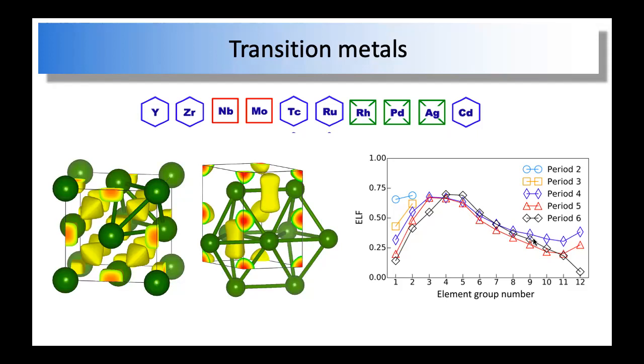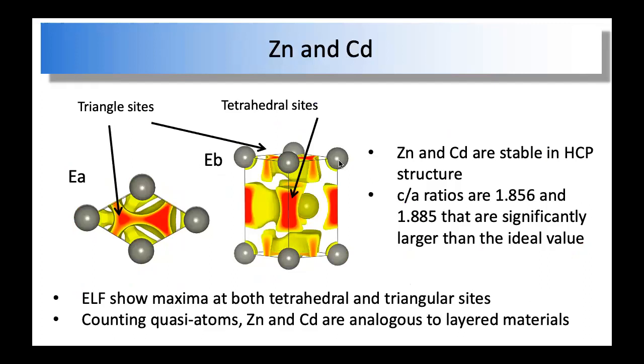So eventually, the localization at these sites is not the determining factor for the structures, and the transition metals in that case prefer the FCC in general, except at the end, group 12, that's zinc and cadmium. You can see a large increase of the ELF at the tetrahedral sites, indicating that for zinc and cadmium, they have a large electron localization on those sites, and therefore a higher chemical interaction there.